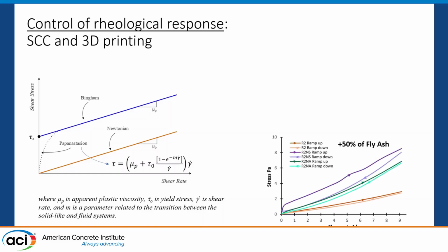And for some systems, like we tested systems with 50% of fly ash and different nanoparticles, you can see that the bottom line is just a reference system with 50% of fly ash, and it is perfect Newtonian response. As soon as you start adding nanoparticles, and I usually use very small quantities of nanoparticles, normally 0.25% of cementitious materials, you can change it to Bingham or Papanastasiou response. And again, you have loading and unloading curves at a certain time period. And so the challenge, again, when we use fly ash in the system, is that it's a challenge to produce the right response.